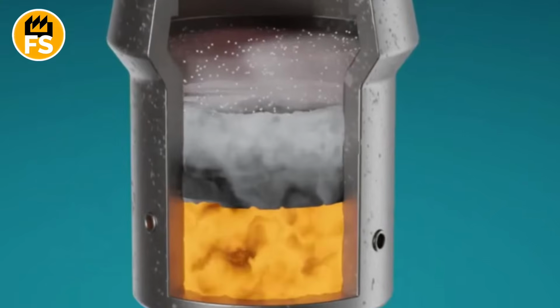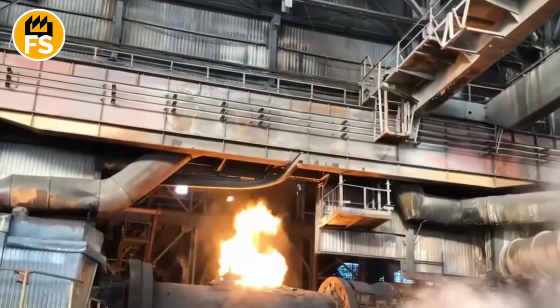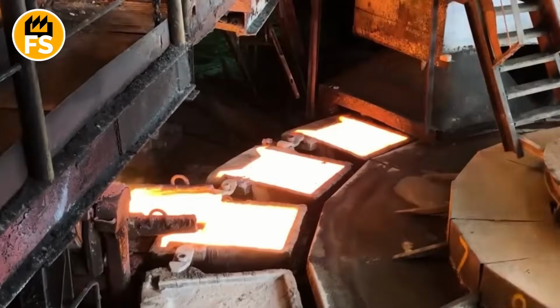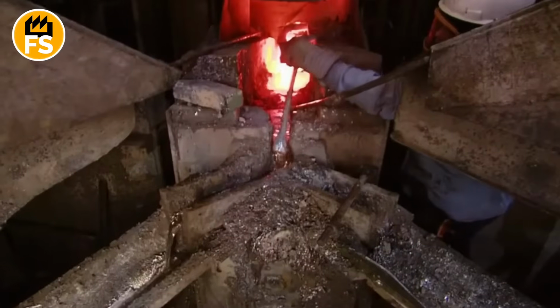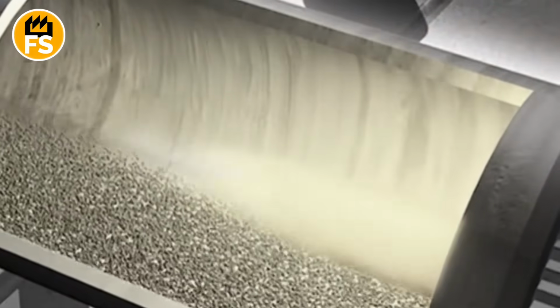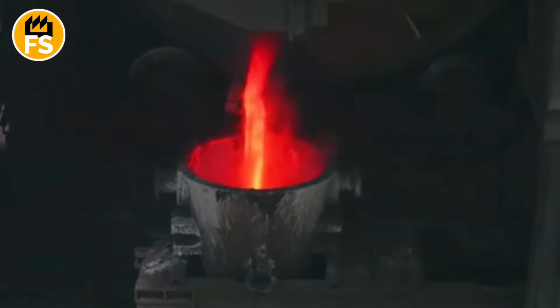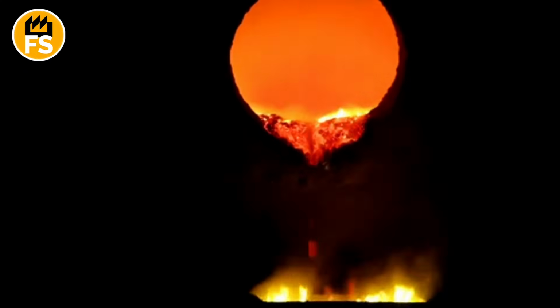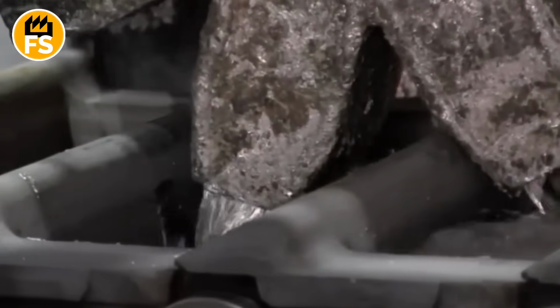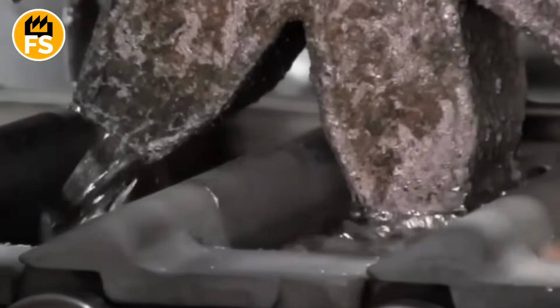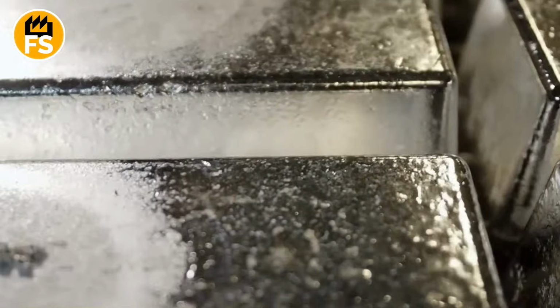The metals stratify, like oil and water, but at the temperature of molten lava. Several layers form in the furnace. Heavy metals, meaning cobalt and nickel, settle to the bottom, while lithium remains in the slag. This is the upper, lighter layer. Then this slag is broken up and processed separately to extract the lithium. After cooling, the metals take the form of small ingots, shiny, smooth, and ready for reuse.